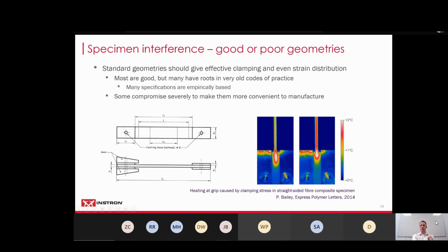You can see, just using thermal imaging, we can visualize very clearly how much extra heat is being generated, indicating there's a lot more aggressive loading just at the point where these specimens are clamped. So if it fails anywhere other than at the grip, there must have been a really big defect somewhere in the gauge section. As I say, a pet hate for me, but you will also find there are some other ones out there which are still in use and aren't great.